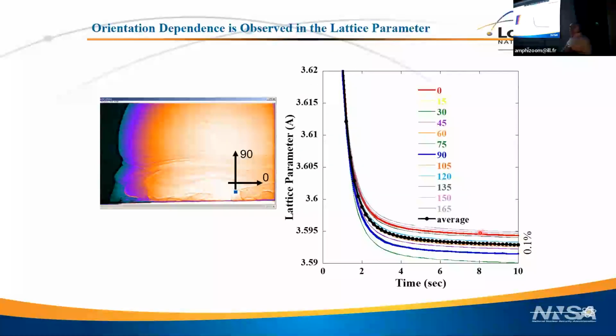If you blow that up, you can see again, that's not noise, it's not uncertainty. That's from the stress in the material. You'll see along the 0 direction, which is parallel to the surface red, the lattice parameter is bigger than you'd expect it to be. That's because the cooling material is trying to shrink, and the cold material underneath it is constraining it, not letting it shrink. So the lattice parameter parallel to the surface is too big. The Poisson's ratio gives you a lattice parameter transverse to the surface that's too small. If you average them all out, you get sort of what the temperature is doing. So that, again, is how we separate temperature from stress.